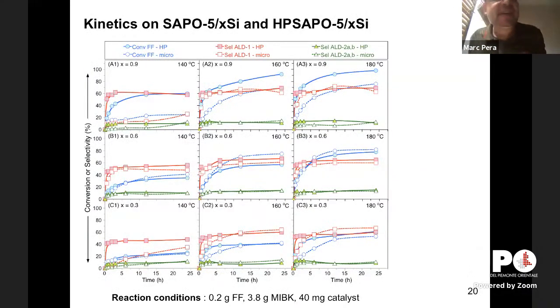So we try to explore this material more in detail. We did a lot of work in terms of kinetic experiments. So just to summarize, the best catalyst was this catalyst with 0.9 silicon. We see always in terms of selectivity for our target product a plateau, more or less at 60% selectivity. What is very interesting is that the conversion, when we compare these straight and dotted lines, that is hierarchical and not hierarchical, we are always much more active when we have the hierarchical structure. So the optimal conditions were 160, 180 degrees, and we stick to these conditions. We have also explored other samples, hierarchical, not hierarchical, other temperature, and this was found the best conditions.